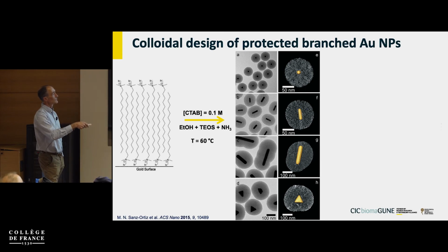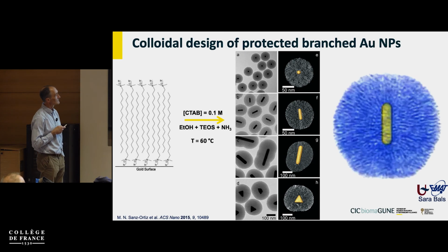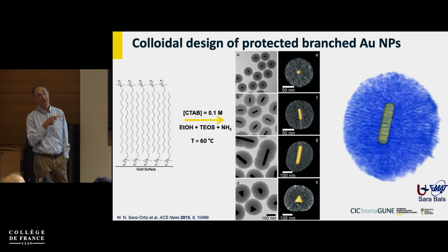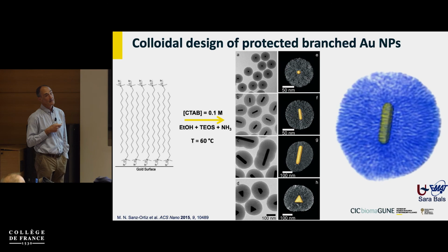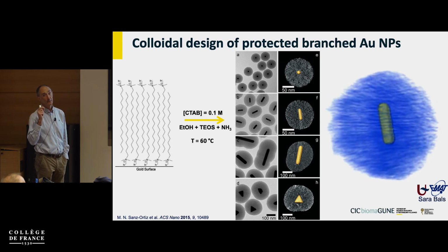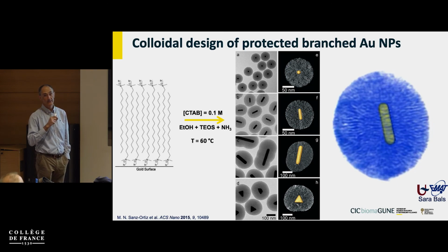Again, these are tomographies coming from our colleagues in Antwerp. And you can see we can obtain not only the coating of different morphologies, but in all cases, it looks like the pores are radial, coming from the core directly to the outside. And if you don't trust me, this is the tomography that shows the same thing. Again, extremely challenging, because now the electron density is very different, and we also have the pores which even lower the contrast.